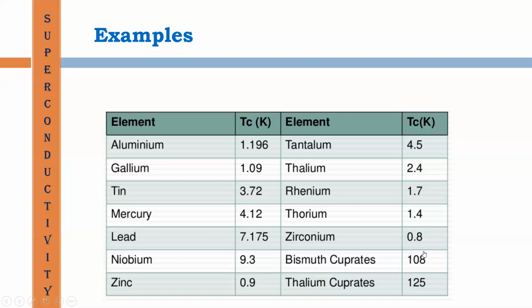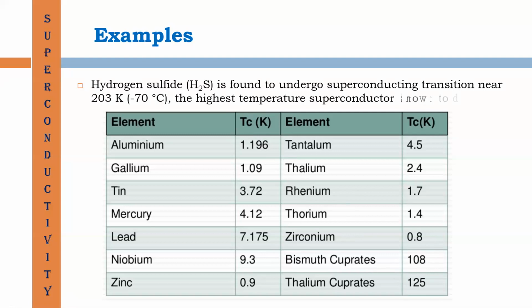These are very high temperatures. Okay, these are some high temperature superconductors, and a recently found high temperature superconductor is hydrogen sulfide, H2S. H2S is found to undergo superconducting transition near 203 Kelvin. That is, it is about minus 70 degrees Celsius. It is one of the highest temperature superconductors known to date.